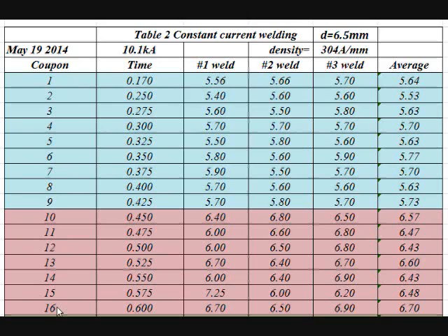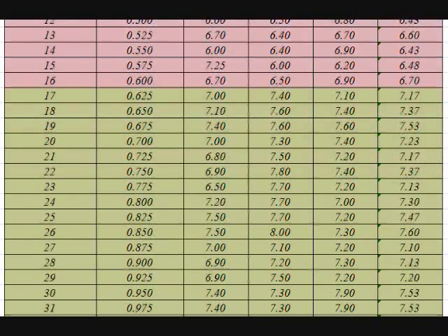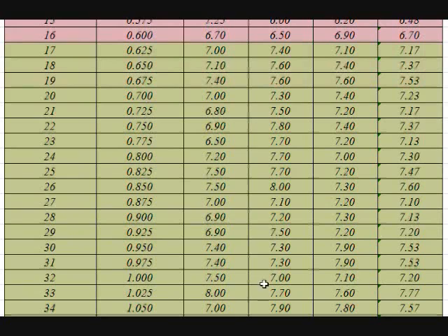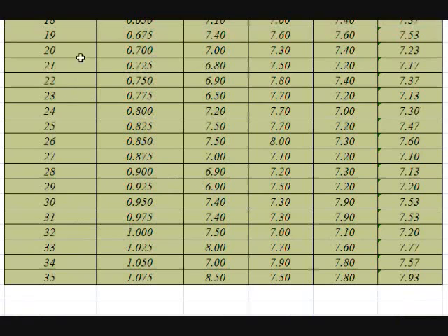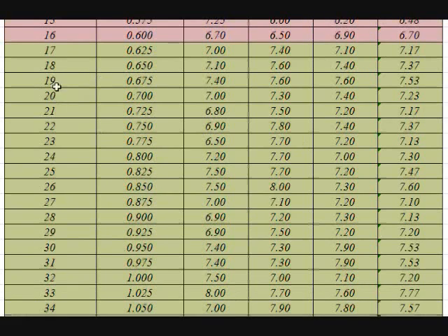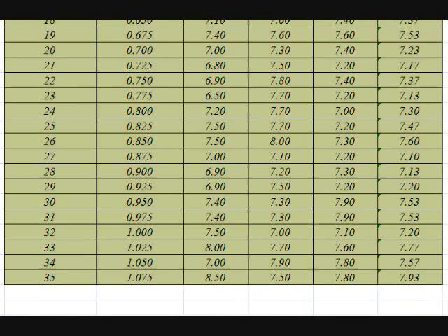Then from coupon 10 to coupon 16, all the nugget sizes are equal to the weld cap diameter. Then from 17 to 35, all the nugget sizes are slightly larger than the weld cap size, so it's getting into the 7 point something range. And at coupon 35, we are still not making an expulsion weld.